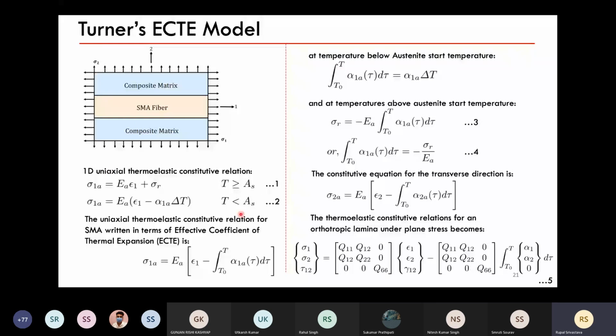And then when it is not in its austenite phase, it is the normal equation that we use for our materials whenever there is temperature involved, conventional materials. Then Turner said that our sigma in one direction for the actuator material, so instead of SMA, as I have used in my modeling, he is using A. So whenever you see A for Turner, it is for the SMA layer. As we are increasing the temperature from initial temperature to the maximum temperature, this is how he envisioned it, where alpha is a function of tau, where tau is a function of temperature, which means that it's a function of temperature. And if we compare equation 1 with this equation, we get that sigma R is this.